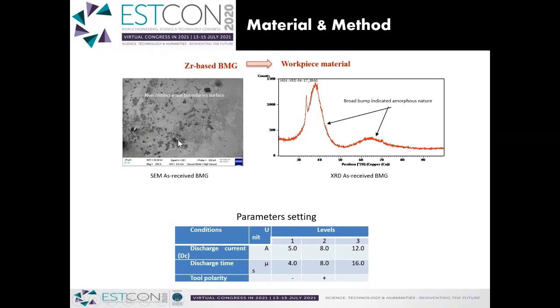As you can see here, this is the morphology of the as-received BMG, in which you can notice there are no distinct grain boundaries. This helps in its unique property, that is, it does not allow dislocation to take place easily. So it has a very high strength compared to the currently used biomaterials, and also its biocompatibility is commendable. This is the XRD. As you can see, a broad bump here, which indicate that it is amorphous in nature and non-crystalline. These are the parameter settings which we used in conducting this experiment.